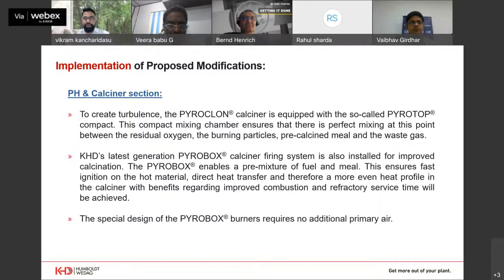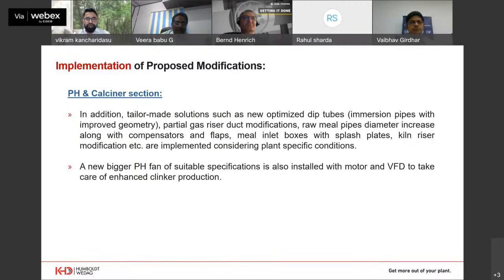The other advantage with the pyrobox calciner is that there is no additional requirement of primary air, which contributes to the heat consumption reduction. Apart from this, in the pyro section, we have done some tailor-made modifications, because case to case, we have to identify these modifications. We have provided optimized dip tubes and done partial gas riser duct modifications. And also the bottom cyclones' raw meal pipes have been increased to suit the capacity. A new bigger preheater fan with motor and VFD is also installed.